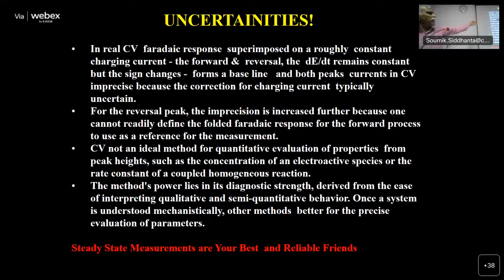So both peak currents in CV are imprecise because the correction for charging current is typically uncertain. Second, for the reversal peak, the imprecision is increased further because one cannot readily define the Faradaic response for the forward process as a reference for the measurement. CV is not the ideal method for quantitative evaluation of properties from peak height, such as concentration of a species, especially for the biosensors people use. Rate constants of coupled homogeneous reactions, etc., are inaccurate. The method's power lies in its diagnostic strength, derived from the ease of interpreting qualitative and semi-quantitative behavior. Once you understand the mechanism, you can use these techniques.